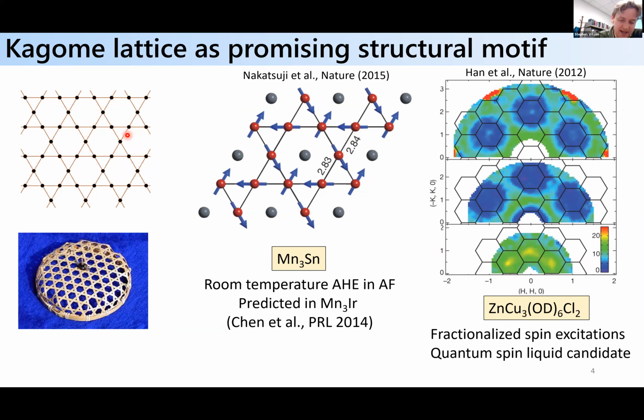In particular, quite a lot of activity has been done looking at the magnetic degree of freedom. Basically, when you decorate a kagome lattice with magnetic moments, and if it's an insulating state, then there are predictions that if you decorate it with highly quantum moments, you can realize quantum spin liquid states. For instance, Herbertsmithite is an example of this, where people look at the spin excitation spectrum and realize things like fractionalized spin excitations, spinon continuum. And so a lot of leading candidates for quantum spin liquid phases are rooted in kagome insulators.